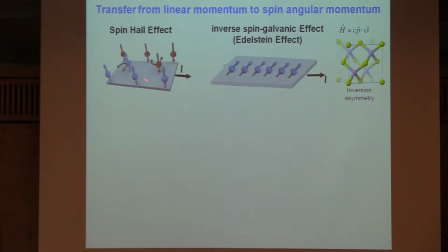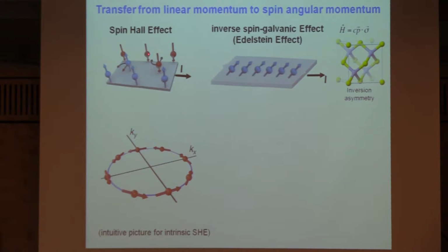So the spin Hall effect in principle generates a spin current, but on boundaries of your system you would accumulate spin polarization, which then can diffuse into a system, for example, in an antiferromagnetic system, and can torque the magnetic orientation in this antiferromagnetic system.